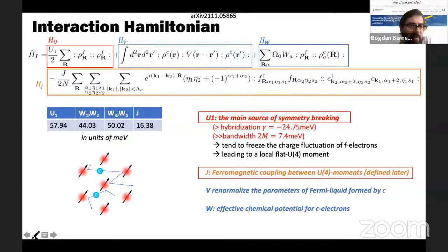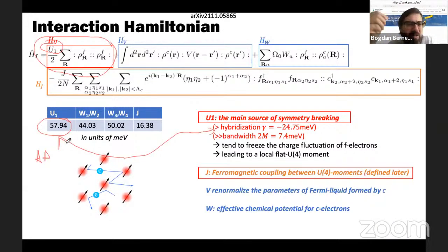And what you get is the following. There are several interaction terms, but the most important one, as predicted, is the density interaction of the f-electrons, these heavy electrons sitting on the AA on the triangular lattice. This is by far the largest energy value in the energy scale of the problem, larger than the hybridization between the F and C electrons. So from the heavy fermion problem, from the Anderson model, you might remember that there are useful models if the coupling between the heavy and light electrons is much smaller than the Hubbard U of the heavy electrons. And this is indeed the case here, computed numerically and now analytically. So this is the largest energy scale in the problem.